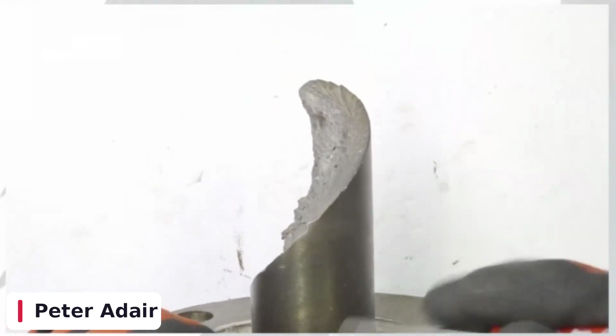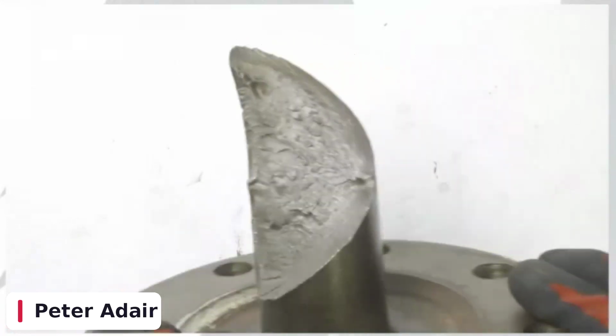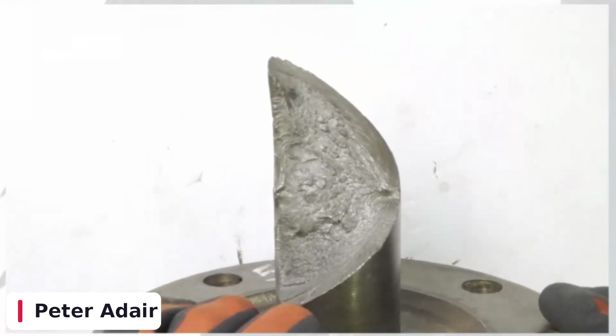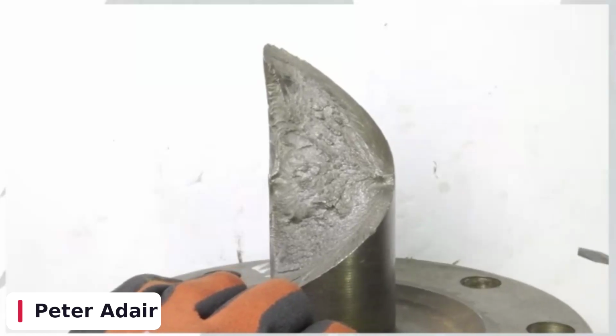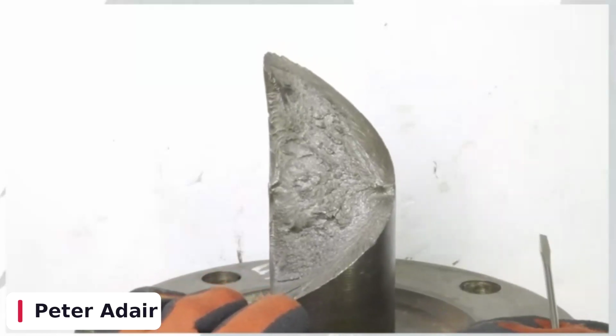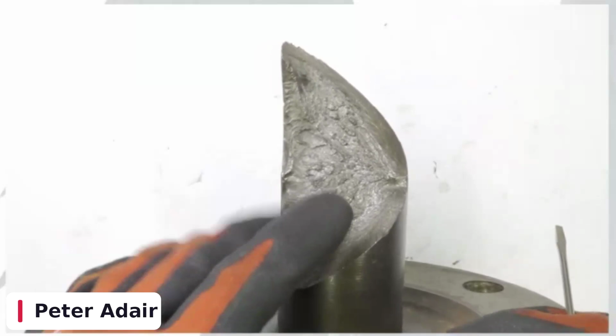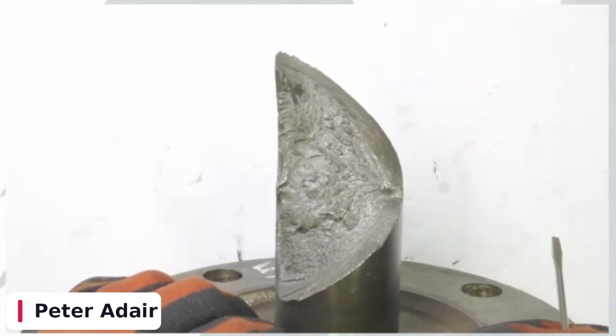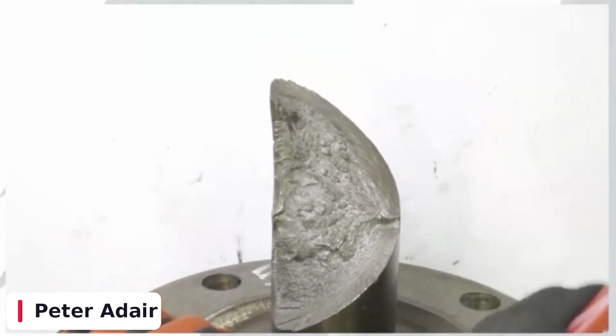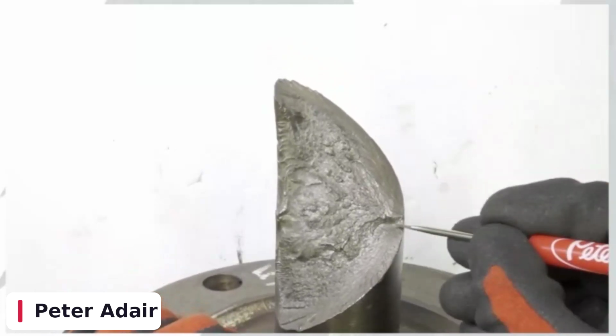So this one is going to be just a pure torsional tensile fracture, meaning this thing was spun up and for some odd reason, the wheel did not want to release that energy and eventually snapped the axle shaft. So again, the grain structure points to a hardened part and a properly made part.